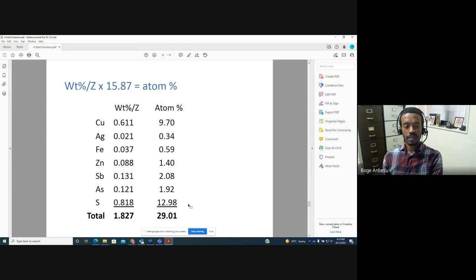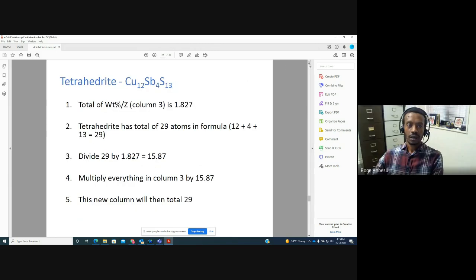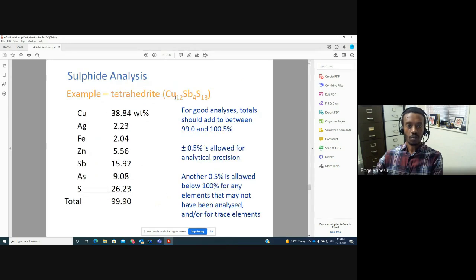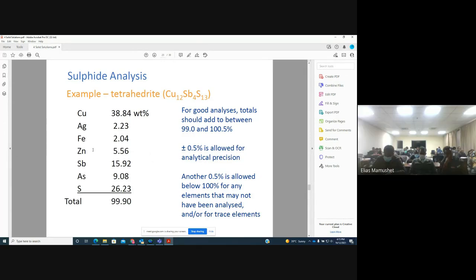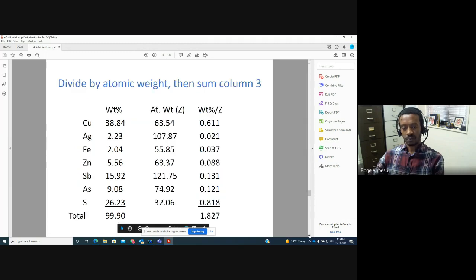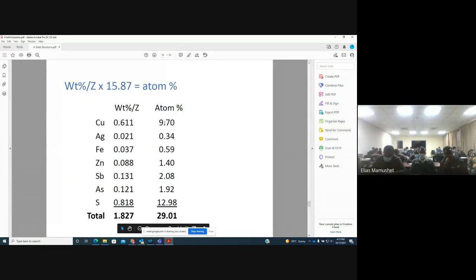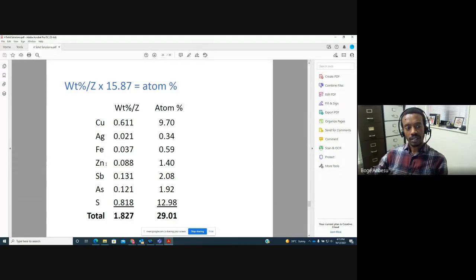And then the next step I would do is, for tetrahedrite, I have a different composition. I have 12 copper, but my calculation shows only 9.7 copper. So as we said earlier, it means the other missing copper is actually replaced by silver, iron, and zinc. That's what this one is showing here. So I add 9.7 plus 0.34 plus 0.59 plus 1.4 and see if this adds to 12, which is the copper. If it adds to 12, then that's very good.